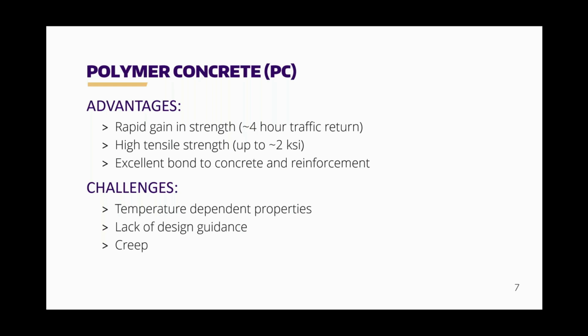And that's because essentially this stuff is glue, right? Where it's a polymer, it's going to have a good bond to concrete and reinforcement. Some of the challenges with polymer concrete that we'll explore today is that polymer concretes, because they have a polymer, have temperature-dependent properties. And characterizing those temperature-dependent properties is important. And thinking about those properties over the range of service temperatures is a design consideration that may not be as familiar as it would be with a UHPC or cementitious concrete. It's a fairly new material, and its use as a structural material is very new, so that there's a lack of design guidance. And because this is a polymer, you have to worry about creep. And creep was out of the scope of our present study, but it's certainly an important aspect that requires further thought.